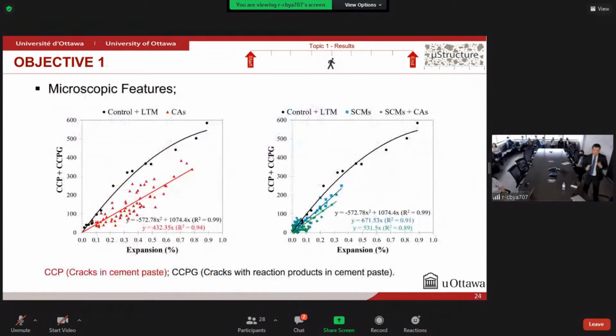And finally, for this objective one, we count the amount of cracks in the cement paste of the ASR affected concrete. And as we can see here, using crystalline admixtures or combining with SCMs or only SCMs alone in the concrete, we can clearly see that we have fewer cracks in the cement paste due to the ASR development. In other words, this proves that first, in enhancing the self-healing of concrete, we were able to change ASR kinetics, but important here is that we were also able to change ASR distress development.